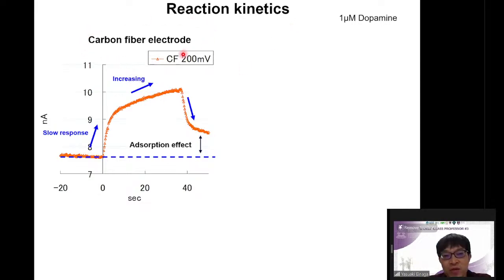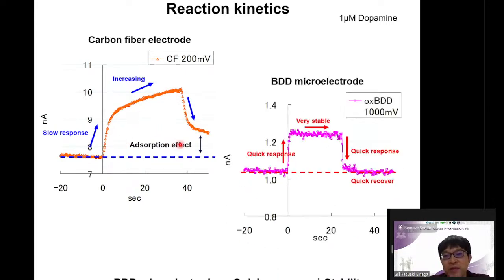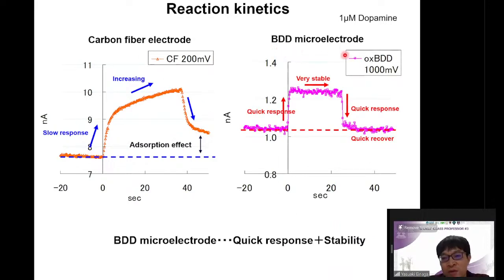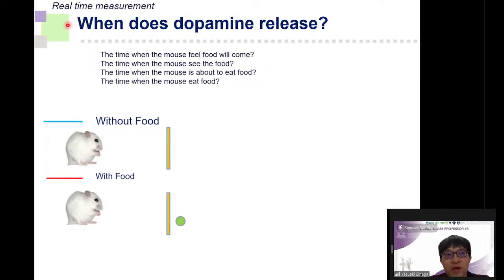And the important point is reaction kinetics. This is a comparison of the carbon fiber electrode with the boron-doped diamond. This is not in vivo; this is a flow cell experiment. As you can see, when dopamine is introduced, the current increases, and when dopamine stops, the current recovers, but the time is a little bit delayed. On the other hand, when our boron-doped diamond microelectrode is used, when dopamine is introduced, the current increases right away, and when dopamine stops, it recovers quickly. It means the response is quick, so we can apply it to real-time measurement.